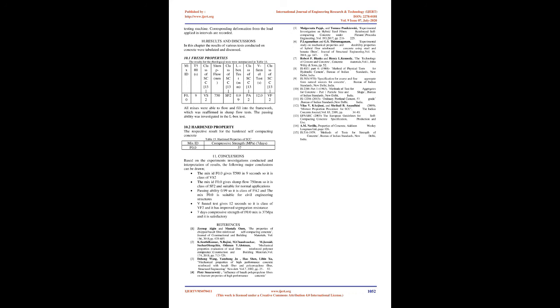11. Conclusions. Based on the experiments, investigations conducted and interpretation of results, the following major conclusions can be drawn. The mix ID F0.0 gives T500 in 9 seconds, so it is class VS2. The mix ID F0.0 gives Slump-Flow 750 mm, so it is class SF2 and suitable for normal applications. Passing ability 0.99, so it is class PA2 and the mix F0.0 is suitable for civil engineering structures. V-funnel test gives 12 seconds, so it is class VF2 and it has improved segregation resistance. 7 days compressive strength of F0.0 mix is 37 MPa and it is satisfactory.